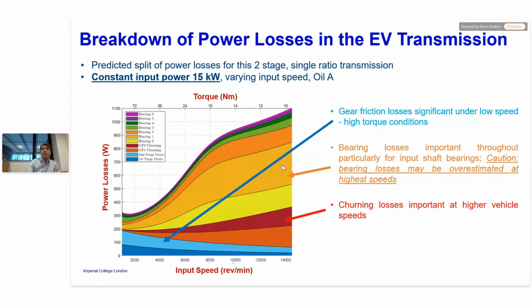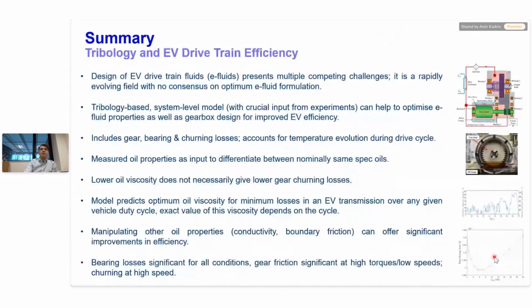I must say this bearing loss includes the bearing churning losses. When I say churning losses here, I'm only referring to gear churning losses. So you can clearly see this evolution of losses with speed and torque. And overall, if you add this up, indeed, our model predicts 10 to 25%, depending on the speed-torque conditions that the vehicle is operating at, of the overall loss is coming from this EDU, which is the numbers I started with. This is my summary.